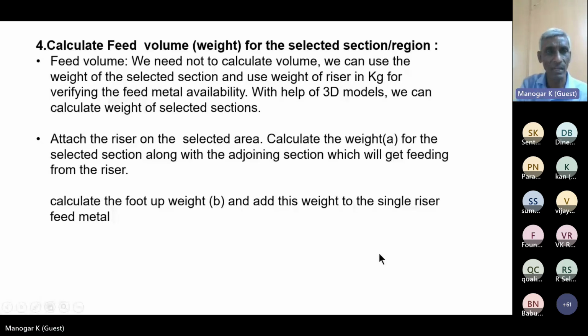Calculate the feed volume for the selected section. Feed volume, we need not calculate the volume. We use the weight from the model. The weight you have to calculate is the casting weight for the given particular riser region, where you have marked the feeding distance and the riser. And along with that, for this example, the flange and the flow bore, there is a 10 mm wall thickness area that will also get self-feeding from the flange. The adjoining area up to the 4T or 5T and the foot pad weight. You have to calculate both the foot pad weight, the adjoining area weight and the job weight.